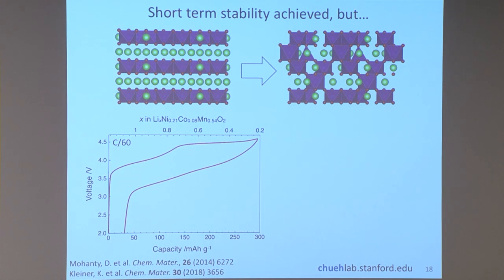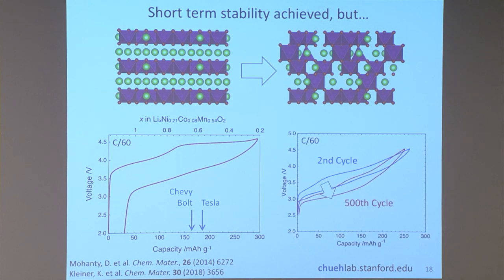An ideal battery should duplicate the curve as you charge and discharge it. But to give you a sense, this is where the Chevy Bolt and the Tesla lie. So we're performing about 40% higher in terms of capacity. So you're able to remove much more lithium. And you can cycle this battery hundreds of times. Now the industrial record is about 1,000 times. So this is approaching the performance of today's lithium-ion battery at a capacity that is significantly higher.